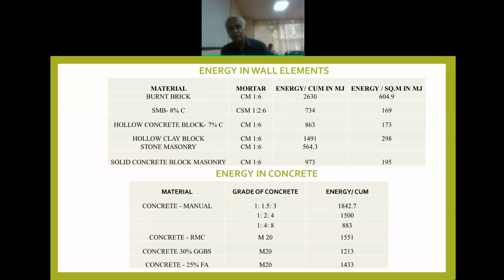Now the other issue is we look at wall elements. Wall elements means you get masonry. Masonry unit. Burnt brick is the basic material. Cement mortar 1:6. So per cubic meter of masonry, the energy is 2630 megajoules. Same if you stabilize mud block with 8% cement in cement soil mortar 1:2:6, the energy is 730. Almost 25% of the energy of the burnt brick masonry. So again, it is a very nice example of how you can save energy and reduce carbon emission.